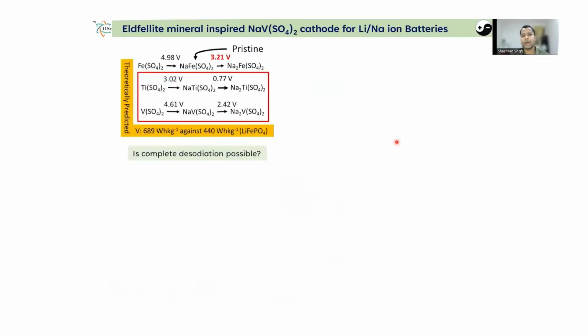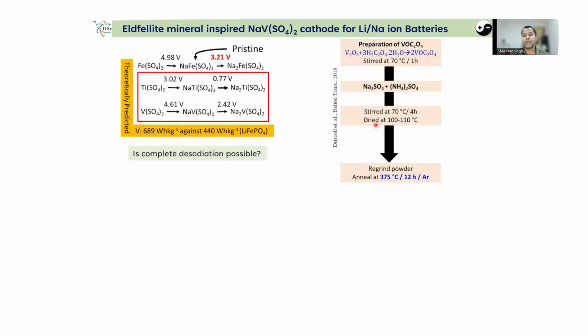Now moving ahead to my third area, it is the mineral-inspired eldfellite-based layered NaVSO4 compound as a cathode for lithium and sodium batteries. In this family of compounds, the first compound reported as a cathode was NaFeSO4 from the Goodenough group, and it was found to show a solid solution reaction at 3.21 volt for sodium storage. In another study, it was found that one can achieve higher energy density if one can have two electron reactions in this family of compounds, and that was only possible in vanadium or titanium based analogs. So we went on to answer whether this is possible, and we synthesized this compound through a solid state route